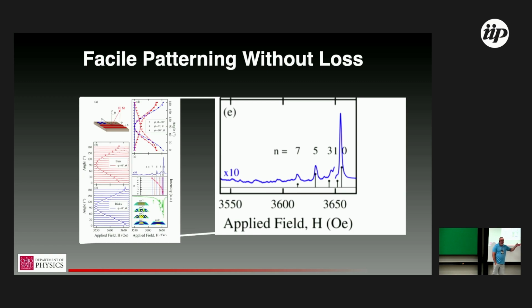And again, the black is analytic calculations using the same input parameters and quantitatively predicting the positions of these modes. So we're excited about a couple of things from these results. Just from a pure mechanical fabrication point of view, it's great to be able to put the material where we want it. That alone is quite useful, and the resonator work Greg talked about yesterday highlighted how that can be important. But more generally, what I think these results tell us is that we really can custom design a magnon resonator. And this is not quite a unique opportunity because, and I think Georg is one of the leaders in this field, you can pattern YIG as well, and pattern it and anneal it, and be careful about the surfaces and how you treat it, and do pretty well.